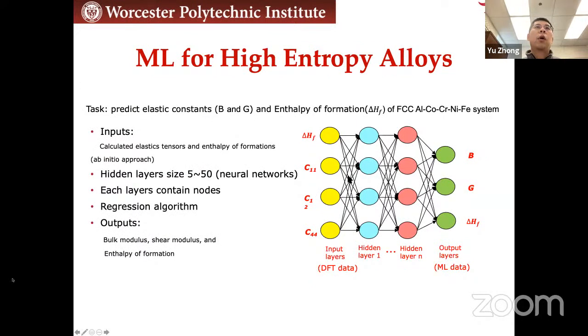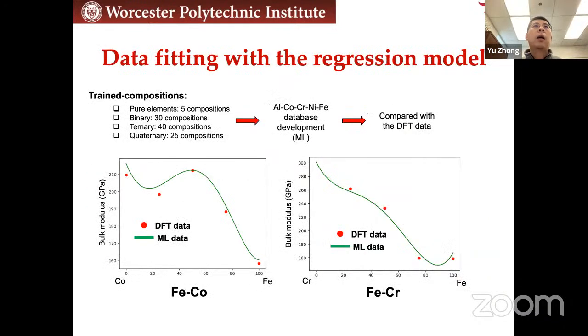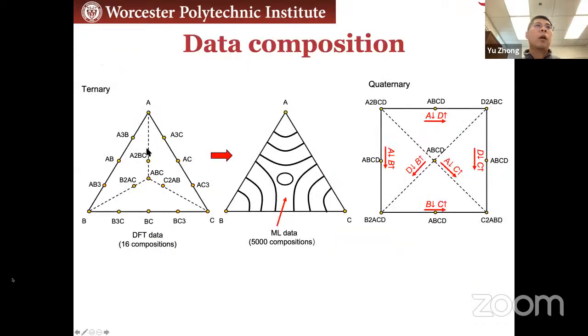Of course, we will also use machine learning to figure out the moduli that we want to predict for all the composition range. That is the key. No matter which composition you are talking about, we will give you a map, essentially. For example, for the DFT data, we get the bulk modulus for different systems, and we did the machine learning, and then we can figure out the whole composition range. These are for two binary systems. And for the ternary systems, these points are the compositions we have calculated.